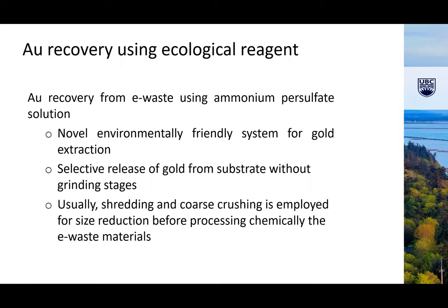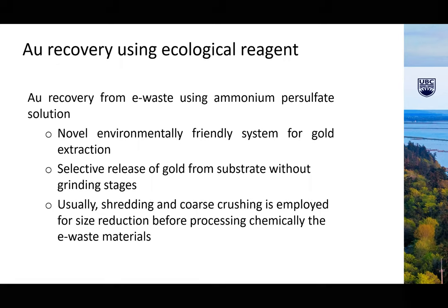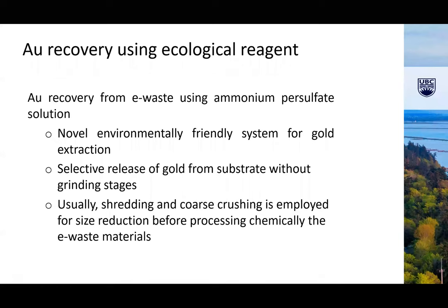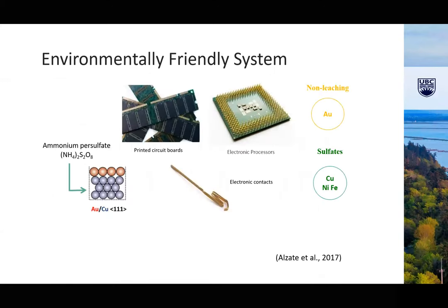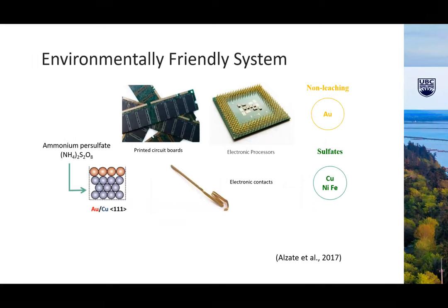peel off the gold. So the idea is that when we have our electronics, usually we don't have a lot of gold. Even looking at your iPhone, you would have very little gold. You have maybe 30 milligrams of gold, and gold is plated on the contacts on electronics. So the moment you start crushing, grinding, shredding this material, a lot of this gold would just dissipate. It will just go into the dust, and you might be losing it.